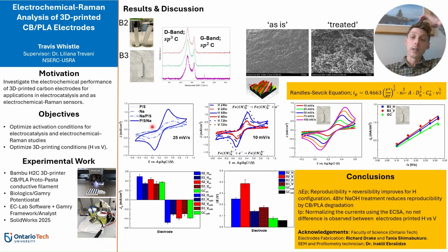Electrochemical studies were carried out in a conventional 3-electrode cell with a platinum counter, silver chloride reference, and carbon black PLA as the working. The studies were carried out using a 1-electron reversible redox couple of 0.5 millimolar ferro/ferricyanide and 0.5 molar potassium chloride as the supporting electrolyte.